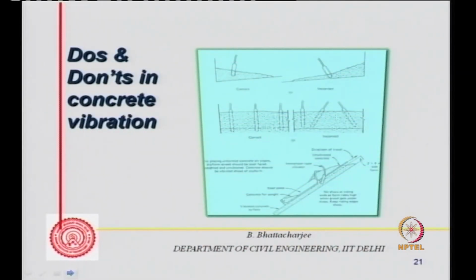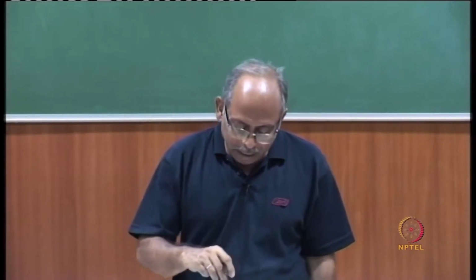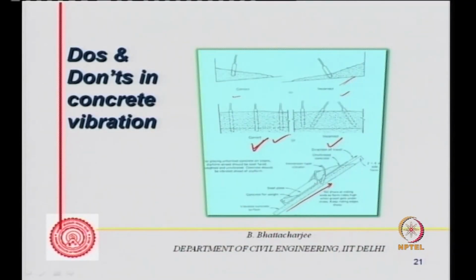What you shouldn't do with respect to vibration: you see, this is the correct type, this is incorrect. The needle vibrator should not be penetrated at an angle. This is incorrect, this is correct, because otherwise they will be dragging the concrete along this direction. So by and large, it should be put down vertically. And if it is on a sloped surface, you place it, do it from the bottom and go upward. So it is desirable that one vibrates vertically downward without inclination of the needle. It is not desirable to incline the needle. And one should not push the concrete by vibration like this being done here. So those are some do's and don'ts with respect to vibration.